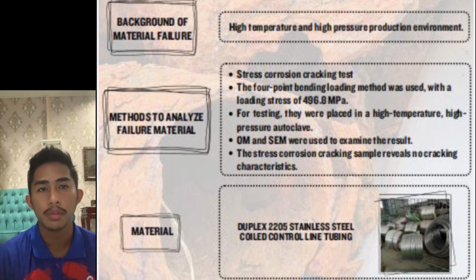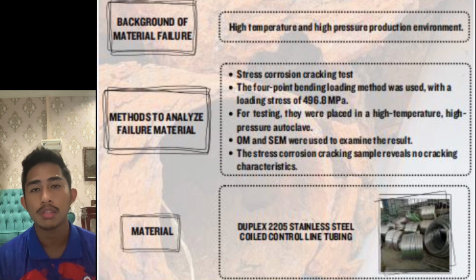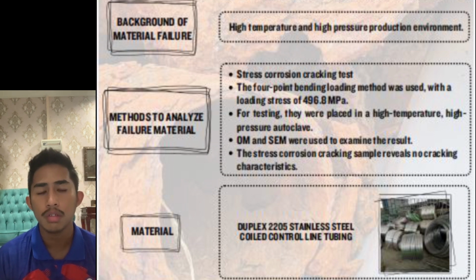Assalamualaikum warahmatullahi wabarakatuh. My name is Akmal, and for my part, I will explain to you about the result of the method that we have analyzed, which is stress corrosion cracking. Through the stress corrosion cracking test, which is simulated with formation water containing H2S and CO2, it is found that the samples have no macroscopic cracking characteristic, but obviously corrosion pits can be observed on the surface of the samples.